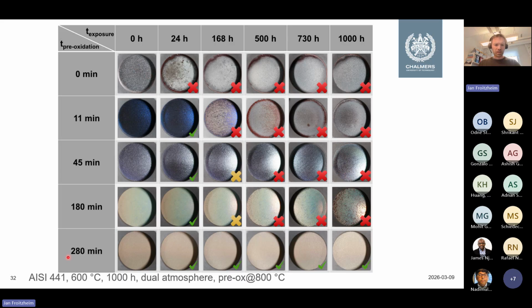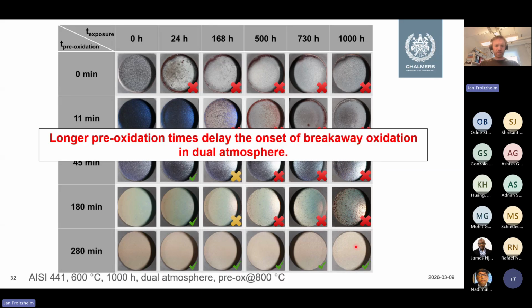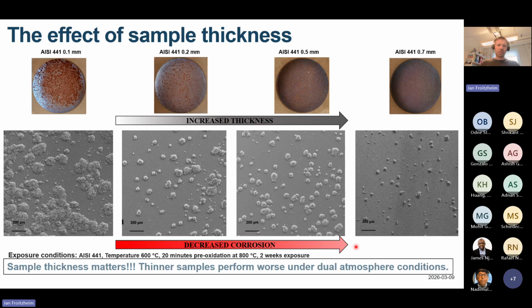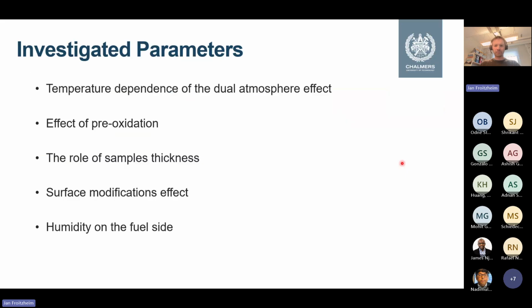We managed to break this 280-minute sample eventually after 5,000 hours, but there is a clear correlation there. Basically we can summarize it that way. We looked at the effect of sample thickness, and somewhat unsurprisingly, if you thin the sample, it's easier for hydrogen to get through. We get a more severe effect, while if the sample is thicker, it's a less severe effect.